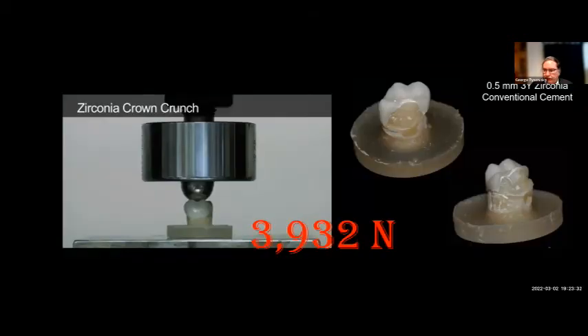Here we're showing the importance of a 3Y material. This is a 3Y material at 0.5 millimeter of thickness, conventionally cemented, and the load to fracture of this material is almost 4 times what a bonded lithium disilicate would be. So again, a very significant resistance to fracture of these types of materials.